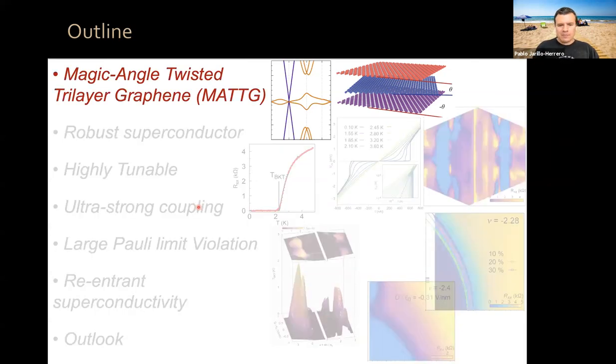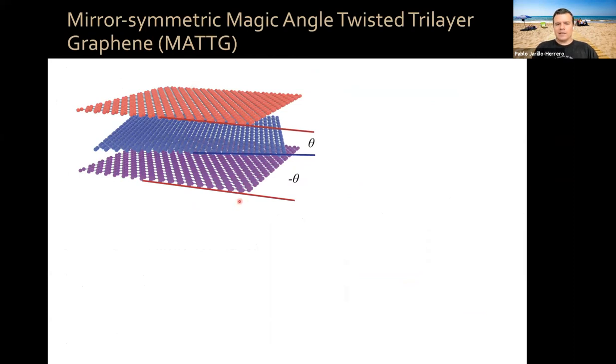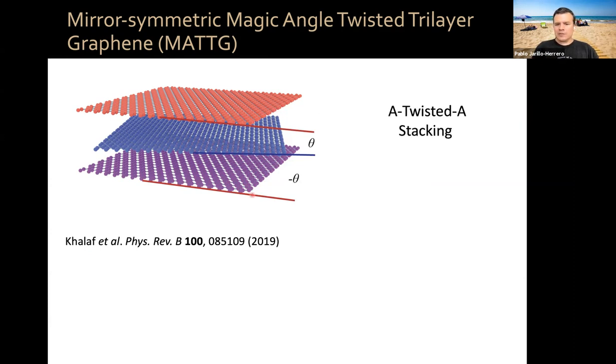Okay, so mirror symmetric magic angle twisted trilayer graphene, or MATTG for short. Now that's a mouthful. Let me show you what I mean by that. I mean this structure. It's three layers of graphene. If you take the bottom layer, now you put a layer on top by rotating it by an angle minus theta, and then you put another layer on top by rotating it an angle plus theta with respect to the middle layer. That means that the bottom and the top layers are exactly aligned on top of each other. Not only are they exactly aligned, in this structure, which was proposed by Eslam Khalaf in Ashvin Vishwanath's group, all of the carbon atoms of the bottom and the top layers are aligned. So this is a configuration known as AtwistedA stacking. And as you can see, this has mirror symmetry with respect to the middle plane.